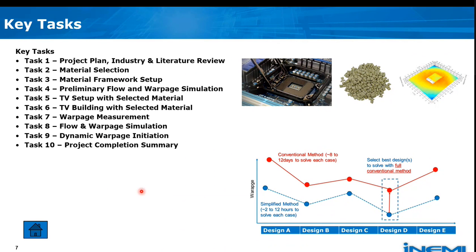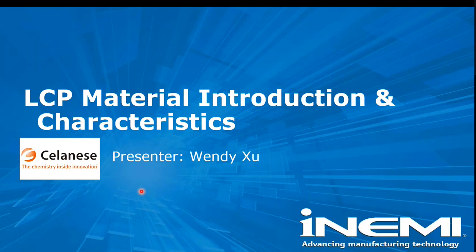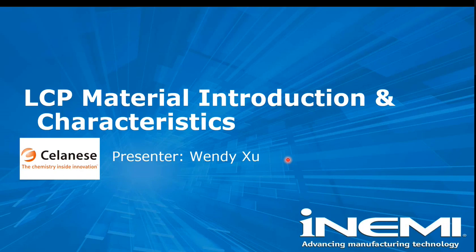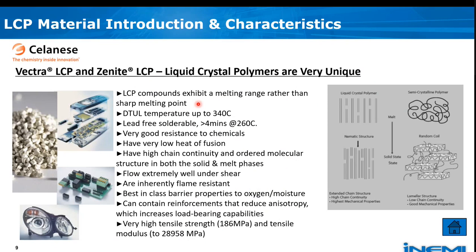In the next session, we invite Wendy from Celanese to talk about the LCP material. LCP is one of Celanese's engineering materials — besides LCP, they also have POM, GR-PPS, and others. CPU socket is a typical and challenging application. Besides CPU sockets, LCP is widely used in connectors and components in E&E, automotive, and other industries because of its unique properties. LCP stands for liquid crystal polymer. Comparing with semi-crystalline polymers, LCP shows a nematic structure in both solid and liquid phases, leading to high chain continuity, very high mechanical properties, and other advantages.